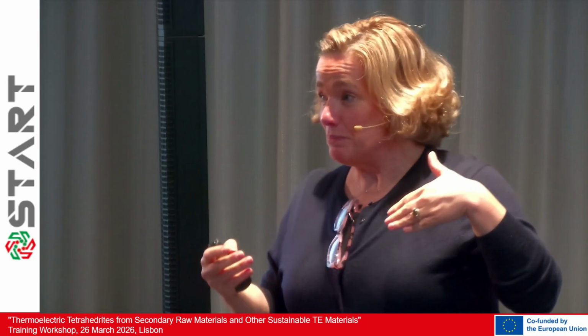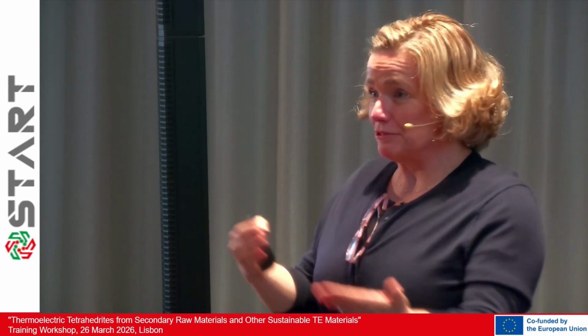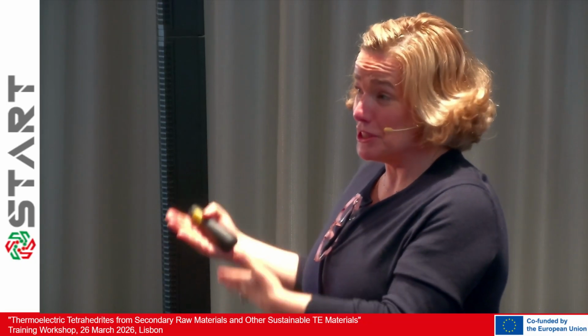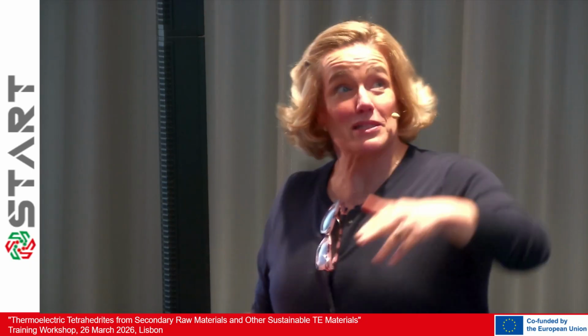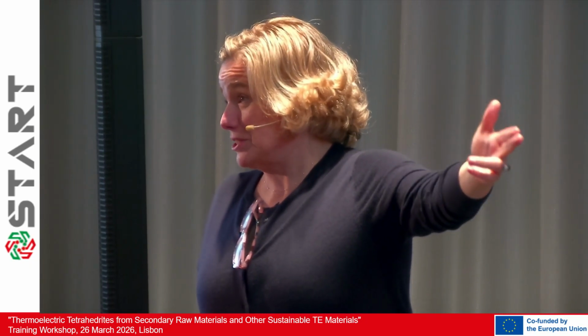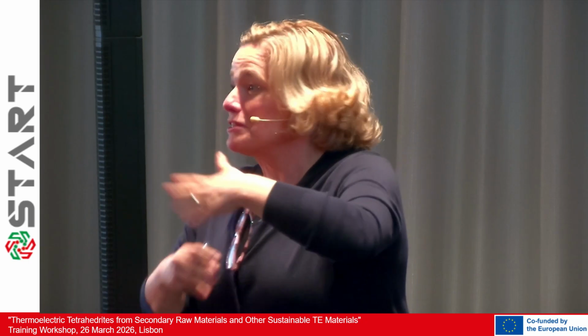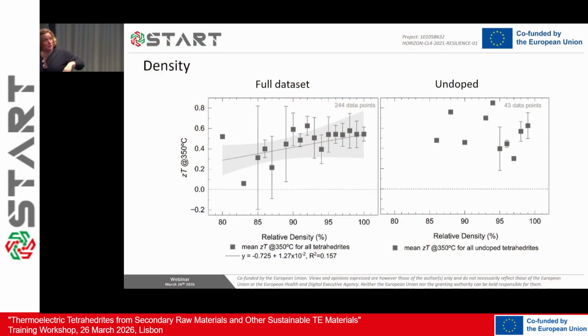Some people put the relative density but don't give the theoretical density. Sometimes they give the density, and that's okay, but most papers don't give the density, they give the relative density. So it's a big mess again, but we try to plot it, and we see a sort of logarithmic function, although here we show a linear fit. Of course, this is terrible because the scattering is huge, but what we can see is that between 90 and 98, the ZT is more or less the same on average.